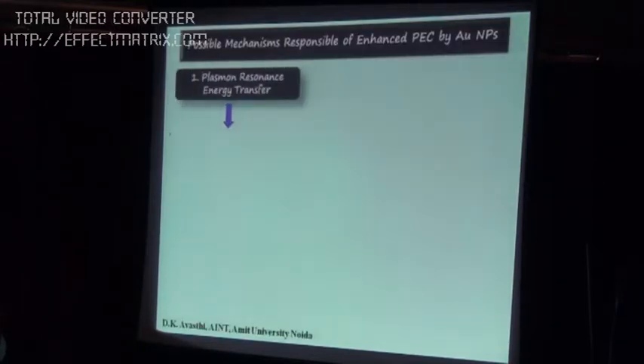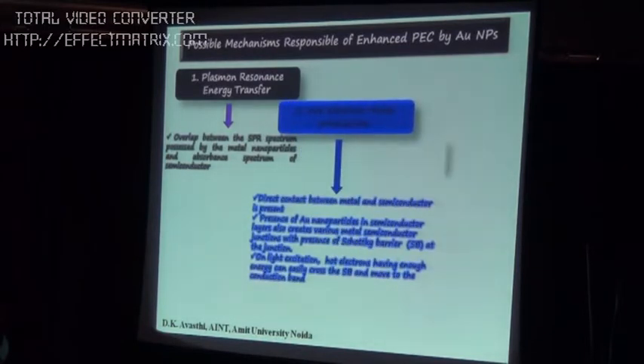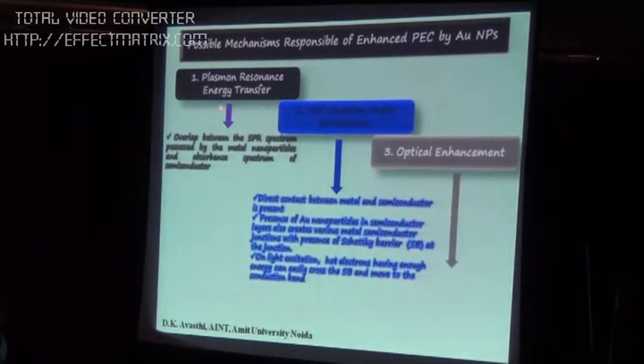So these are the possible reasons for that. One reason could be plasmon resonance energy transfer. That means there is an overlap between the SPR absorption and the absorption of the semiconductor material. The second could be related to the Schottky barriers, which are producing hot electrons that go into the circuit. And the optical enhancement is also there, due to scattering of photons by these large particles here. So these are the different reasons that could be given for that.